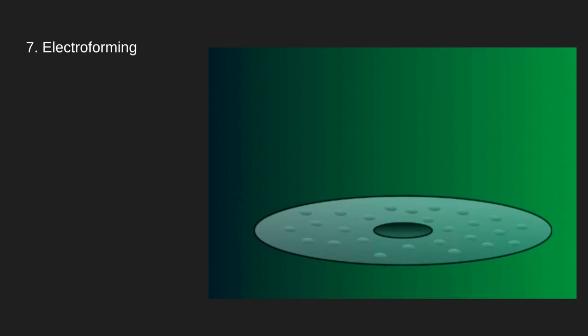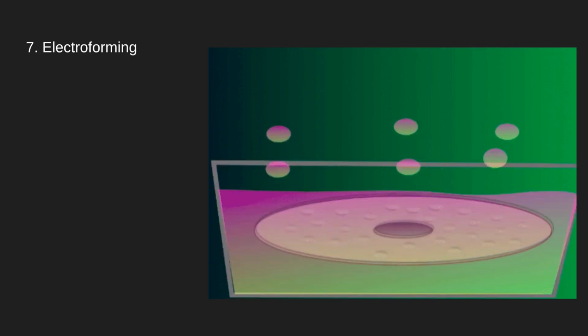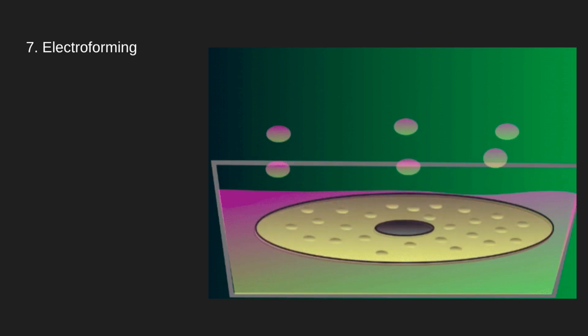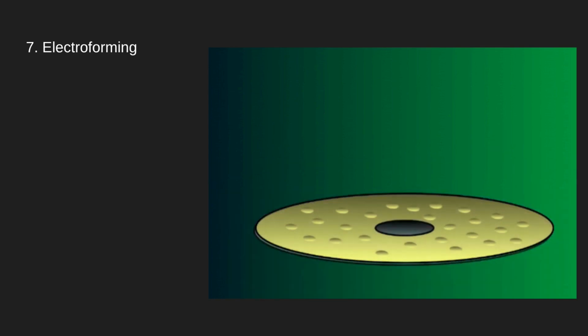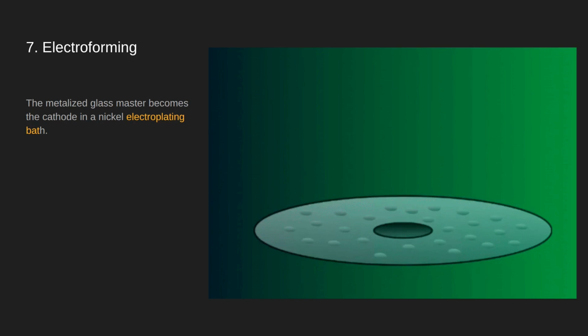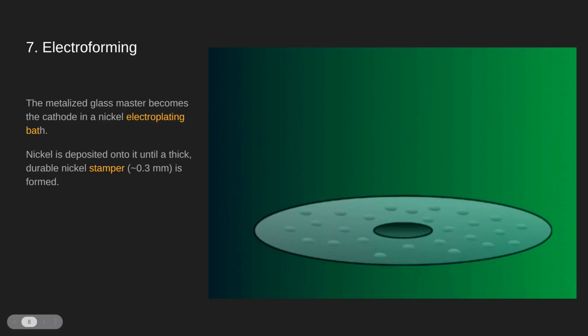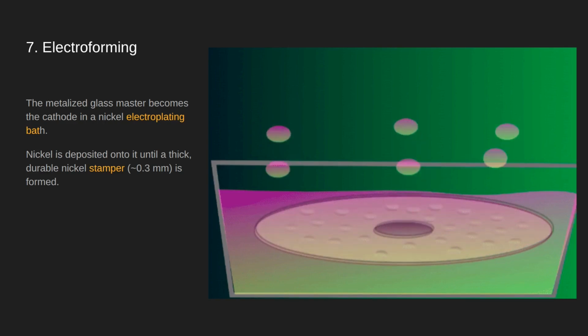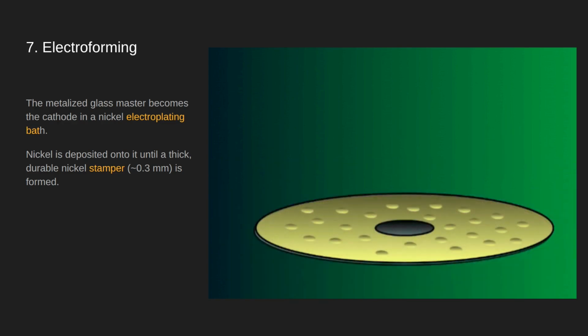What we now need to do is increase that thickness of the nickel so that we can actually peel off a whole metal impression that's going to be used later on. So we're going to peel off a whole metal disc. And the way that works is you plug in the nickel side into the cathode. That becomes the cathode. And through electrolysis and electroplating, a thicker layer of nickel is built up on top, building upon that existing layer. And it keeps on building up until about a 0.3 millimeter thickness layer is formed.